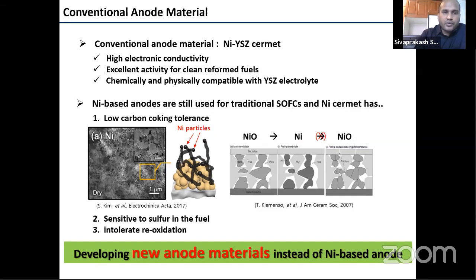But when we use hydrocarbon as the fuel, it undergoes severe degradation because nickel is a very good carbon catalyst, so carbon fiber is formed on the nickel material. This carbon fiber eventually breaks the fuel cell, even within 1 or 2 hours of operation.